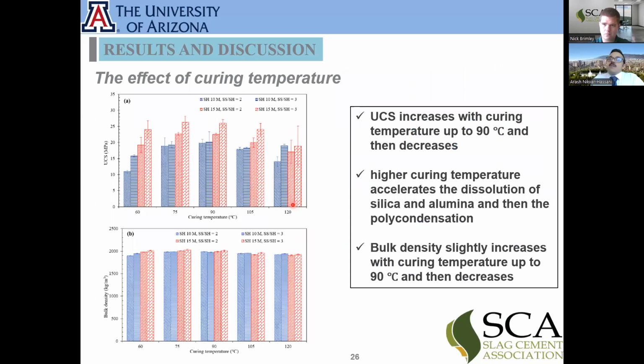Now, after determining which percentage of slag is good, we said, okay, now what about the temperature? How much heat should we expose these samples to so the curing can be completed? So we put the samples in the oven from 60 degrees to 120 degrees Celsius, and we check the samples' UCS, compressive strength, at 7 days. By checking this graph, we see that obviously there is an increasing and decreasing trend. That means by increasing the temperature from 60 to 90 degrees, we are having better geopolymerization. The strength is higher, but then we see a slight decrease. Is there a specific reason for this? We are going to see it in the microstructure studies too, but yes, there is a reason.